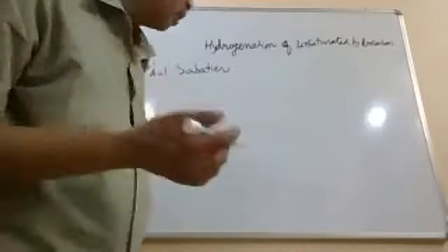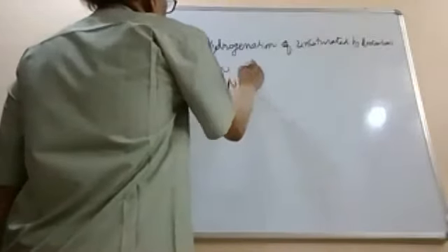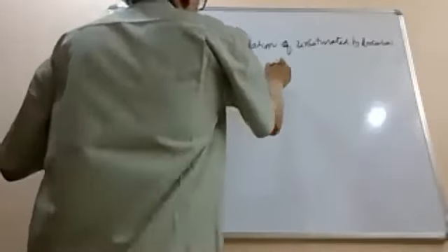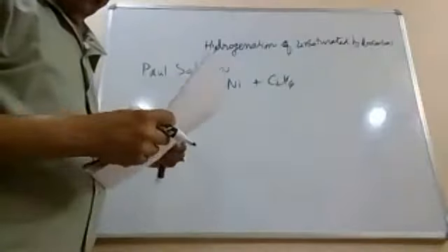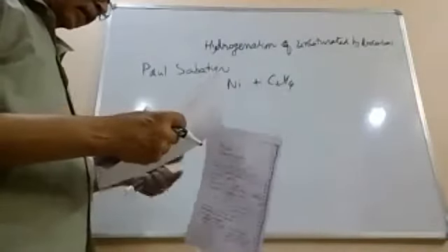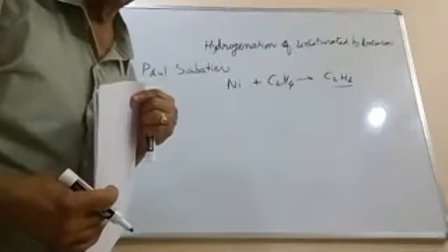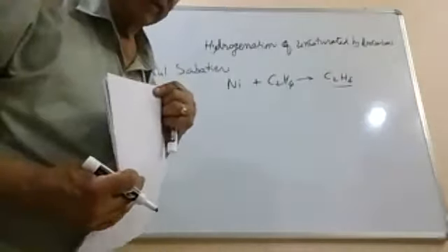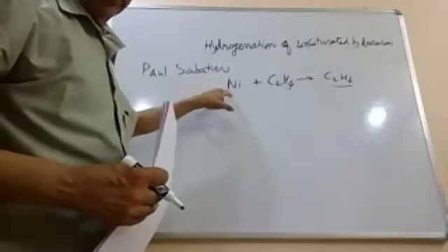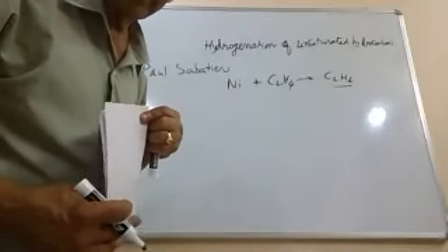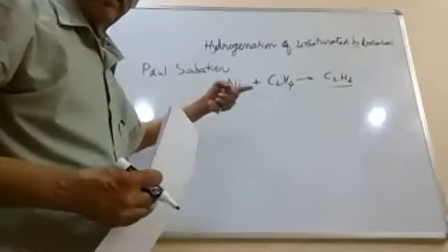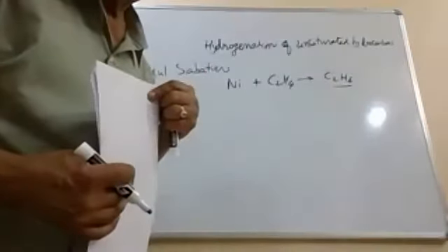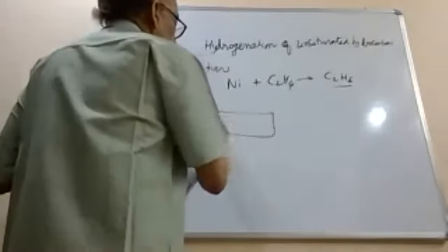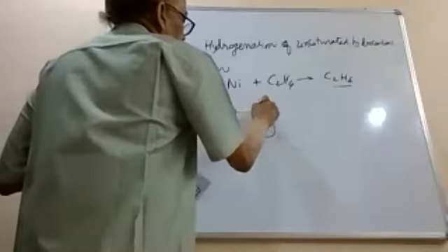In fact, what Paul Sabatier was trying to do was make nickel and ethylene complexes. All right, when he was trying to make nickel ethylene complexes, what he found was he was able to saturate that double bond in the C2H4 ethylene to make ethane. That was unbelievable. If you change this nickel to cobalt or iron or copper or tungsten, this reaction won't work. So the nickel here is a magic catalyst, and it's even used today in industry. It's called the Sabatier process, where you take finely divided nickel, extremely dispersed. This is called Raney nickel.